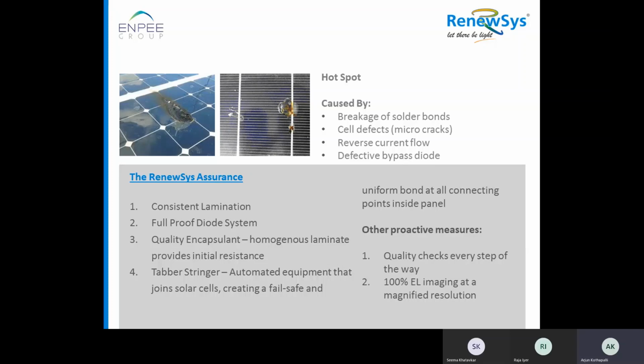Tabber stringer is another source where solder joints may break because of loose soldering or loose tab pull strength. Here in RenewSys we have tabber stringers from Europe, which have consistent soldering, where the tab pulls are uniform across the module. Another proactive measure is quality checks at every step, and we do 100% EL at 2 stages in the line, that is pre-EL and post-EL. Pre-EL is before the lamination, and post-EL is after the lamination. So we have total control on the quality of the cells and the modules we are sending out from the factory.